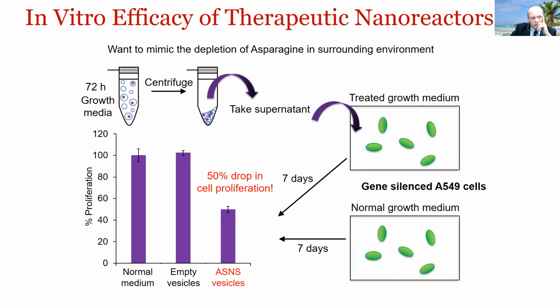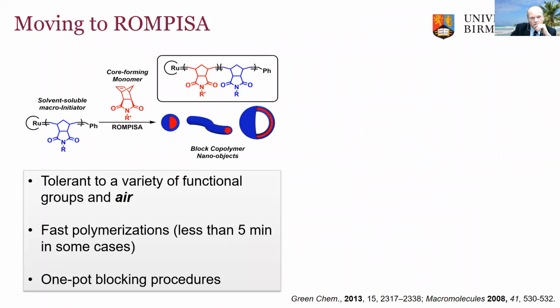So we've done all of this with RAFT polymerization. We also were interested in moving to some other polymerization mechanisms to try and explore a bit more the versatility of the PISA process. So we became interested in using ROMP PISA, so using these norbornene type monomers. One of the advantages with ROMP is that it's very tolerant to a variety of functional groups, and also to air, so really very fast as well. And we proposed that we could think about taking, if you imagine we have our solvent soluble macroinitiator, again using the same principle of having a core forming block and then being able to make these nano objects.